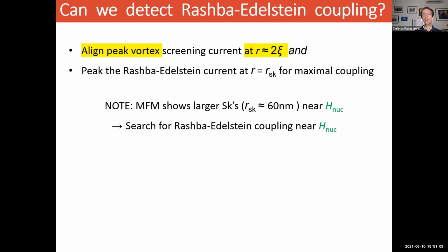Now, we find from our magnetic force microscopy measurements, when we look at our magnetic skyrmions, that as I go closer to the nucleation field, the skyrmions tend to become a little bit larger. Actually, I mentioned our skyrmions are approximately 43 or 45 nanometers in radius. When I get closer to the nucleation field, they grow to approximately 60 nanometers. So if I am to look for Rashba-Edelstein coupling, then I should be looking at skyrmions in the presence of a magnetic field which is near the nucleation field. And that's what we did.